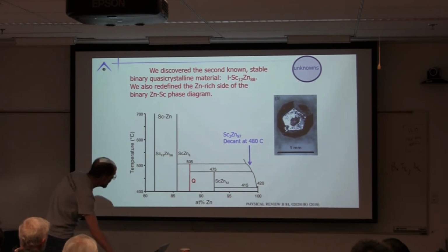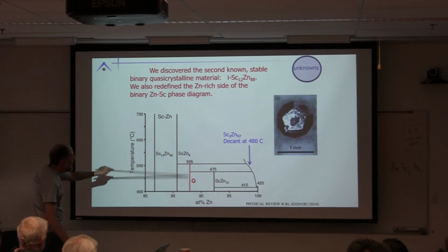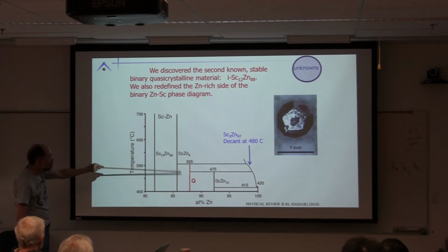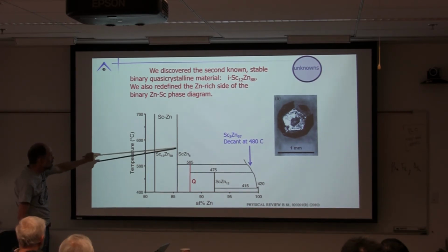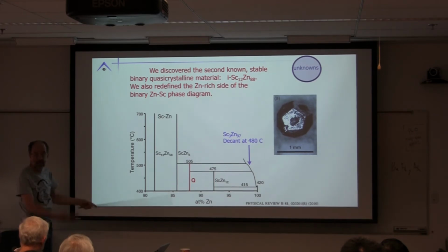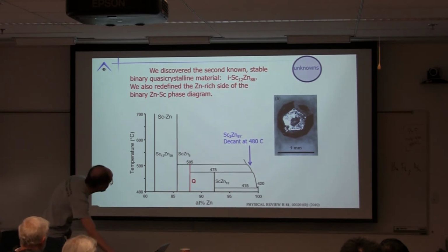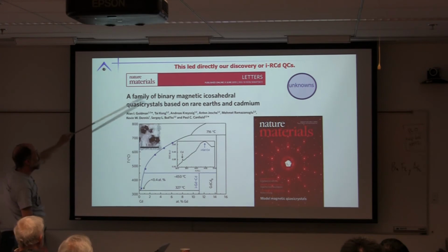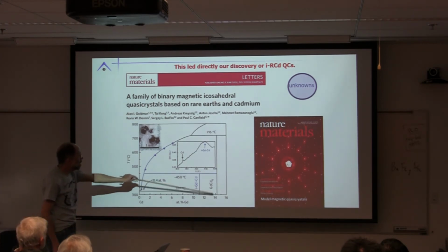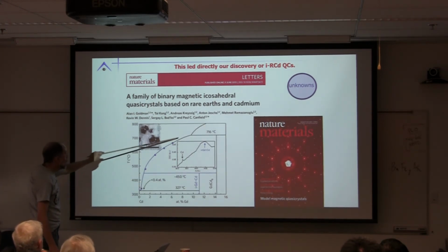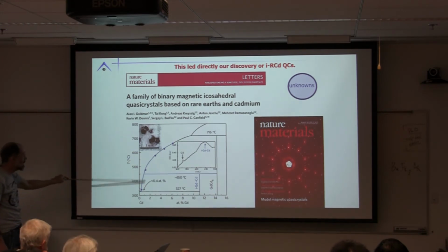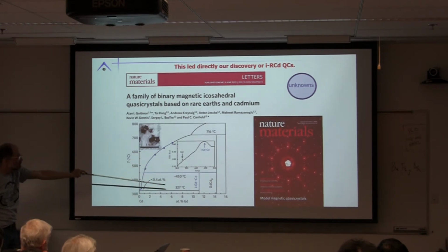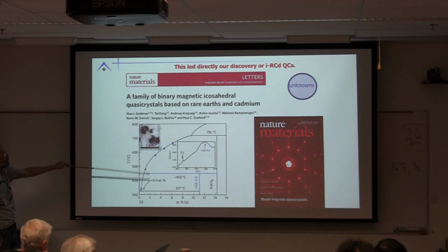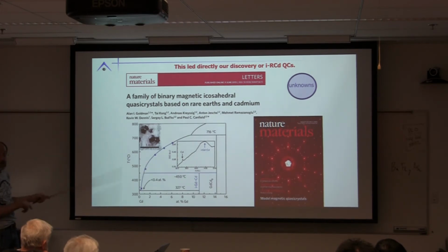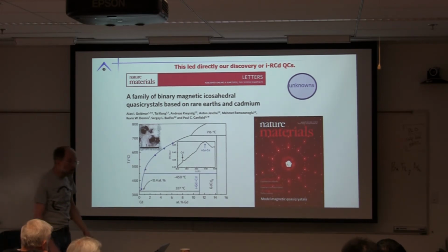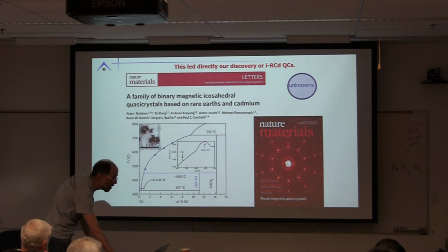Okay? But in doing that, we speculated that maybe you could find quasicrystals close to, as sort of deep peritectics, what are called crystalline approximants, things that have similar structural motifs. And with that idea, we went and looked at the rare earth cadmium series. You have rare earth cadmium 6, and we redefined the liquidus line and found a new quasicrystalline phase, another binary quasicrystal, but in this case, with moments, so we can again look at the spin glass physics in binary systems. All right.